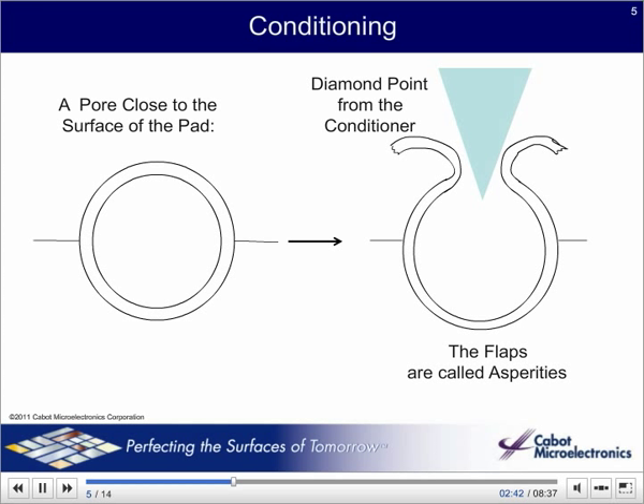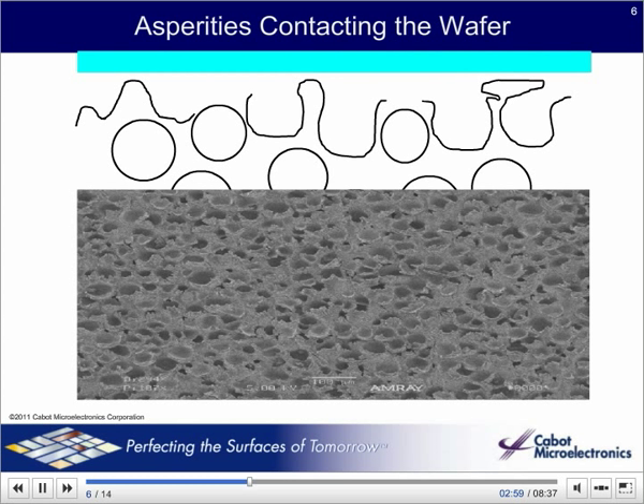After polishing for a while, the asperities soften, maybe melt, get caked with debris, lose their resiliency, and need to be replaced. The diamond conditioner continuously or intermittently shears away the pad surface and creates new, fresh asperities. This drawing was adapted from Len Borucki's work at Araca, showing how different asperities might contact the wafer. The picture below is from Abhi Prasad, showing what the asperities look like under high magnification.